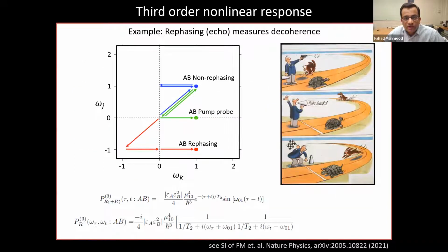And so if I were to measure this rephasing peak, then I can directly measure the decoherence time of my system, T2, right? And this rephasing peak, if you're familiar with Hahn spin echoes or NMR echo techniques, is very similar to that, because what's happening is you have an ensemble of two-level systems. They're all decohering with some characteristic rate. And so as you move time forward, they all start to dephase from each other.